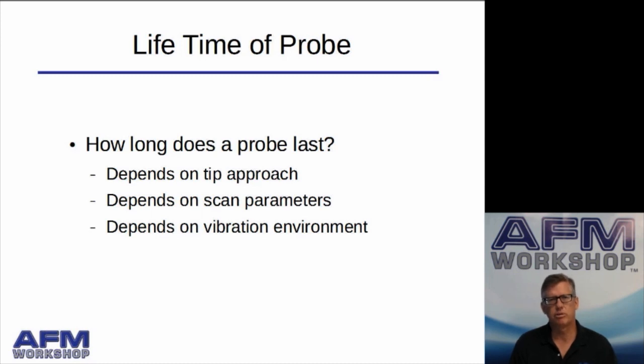Second, it depends on the scan parameters you're using. If you start to scan too fast and the feedback loop in the microscope can't keep up, the probe tip will tend to be chipped off. Then as time goes on, you'll see the resolution of your microscope degrade. Also, it depends on the vibration environment of the microscope. If the microscope is vibrating a lot and the tip is being pushed into the surface of the sample, then that'll cause the probe to break.